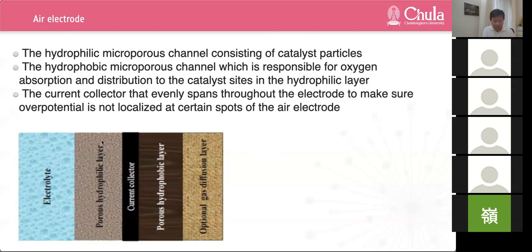It has a hydrophilic layer, a hydrophilic microporous channel consisting of catalyst particles here, and the hydrophobic microporous channel, which is responsible for oxygen absorption and distribution to the catalyst site, a porous hydrophobic layer, and the current collector that evenly spans throughout the electrode to make sure overpotential is not localized at certain spots of the air electrode. And for the hydrophilic layer, it is vital that the hydrophobic PTFE, polytetrafluoroethylene binder, is kept to a minimum to maximize electrolyte exposure at the catalyst site.